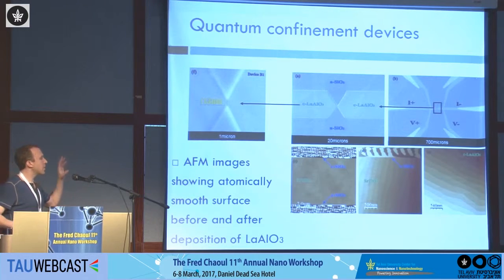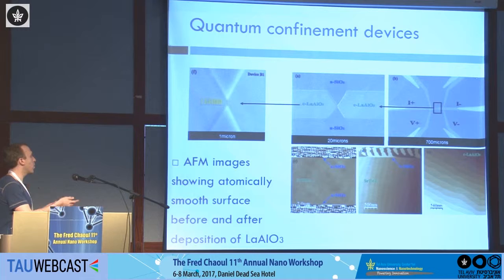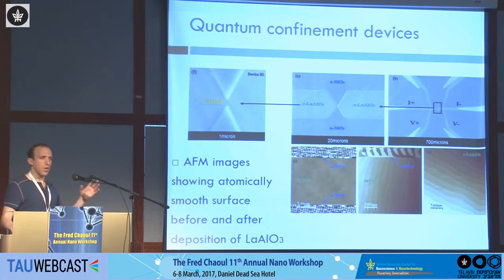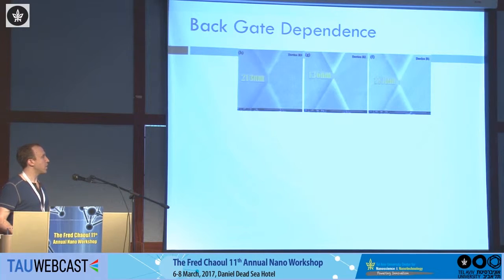Not only that, we want to see that this interface, or the surface, is clean after all this new method. So we did an AFM scan before deposition and after development of this HSQ, and after deposition of LAO, and we saw our atomically smooth STO or LAO, which showed that no contamination has occurred on our material. So we got the device, and what we'll have to do is take the device and cool it down in liquid helium, and this is what we've done.